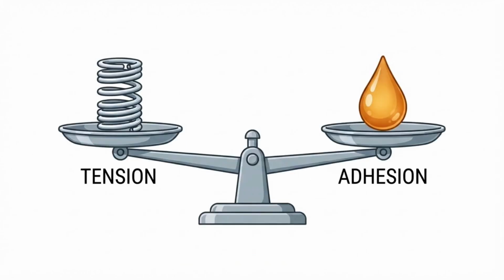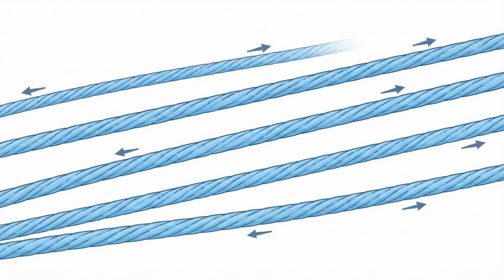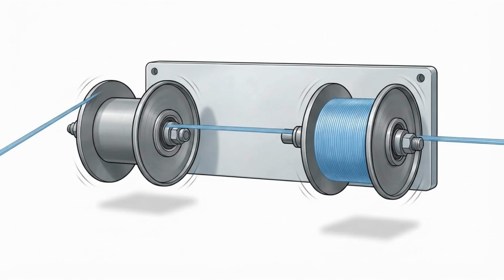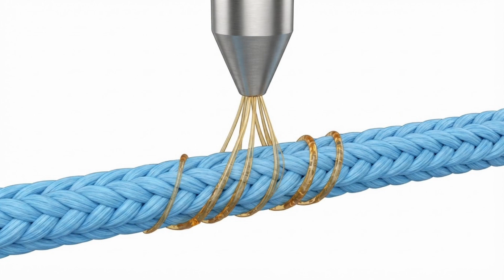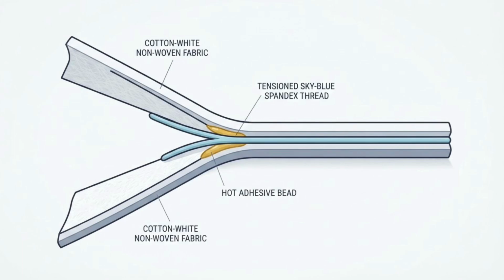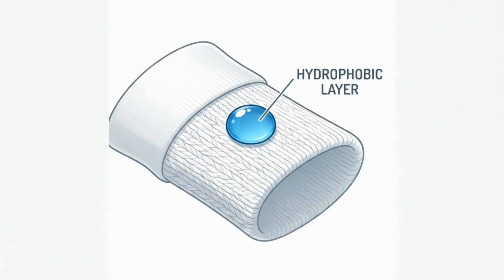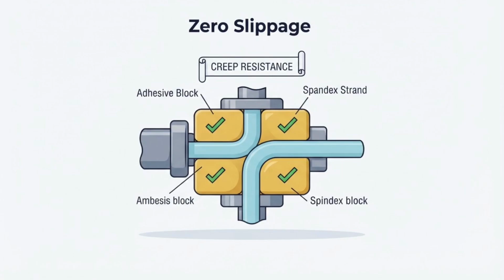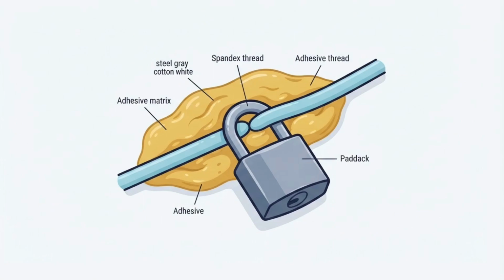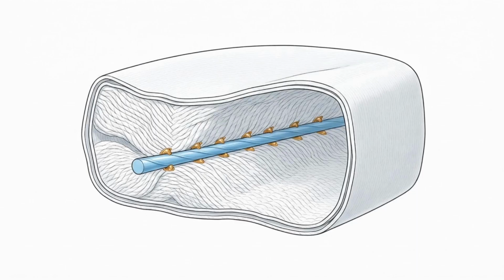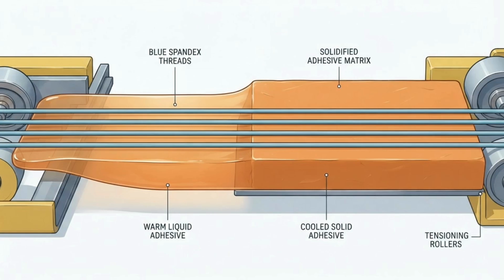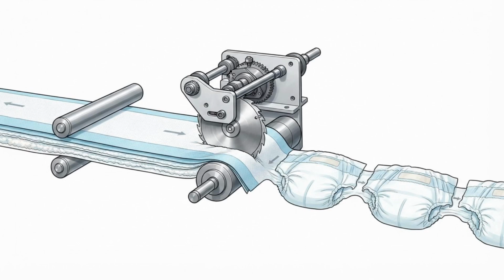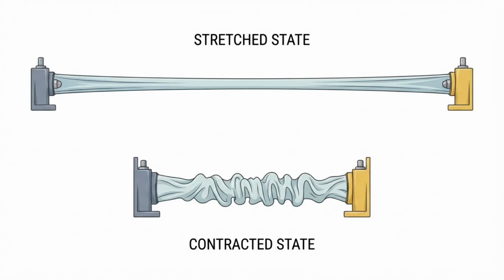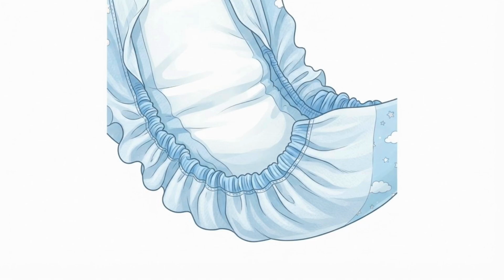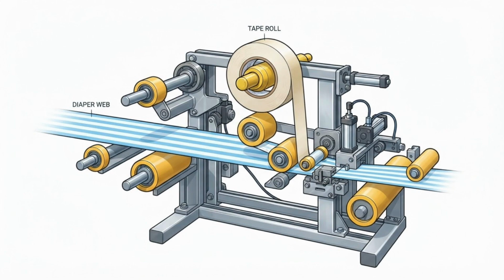Applying the elastic strands for the leg cuffs involves a delicate balance of tension and adhesion. Continuous threads of spandex are aggressively stretched as they are pulled from their spools. Hot melt adhesive is applied directly to the stretched threads, which are then sandwiched between the layers of the hydrophobic cuff material. The adhesive must have exceptional creep resistance, meaning it must instantly lock the highly tensioned spandex into place and refuse to yield, even when the hot glue is still cooling. When the final diaper is cut and the tension is released, the spandex snaps back to its original length, gathering the fabric into the familiar ruffled leg cuffs.